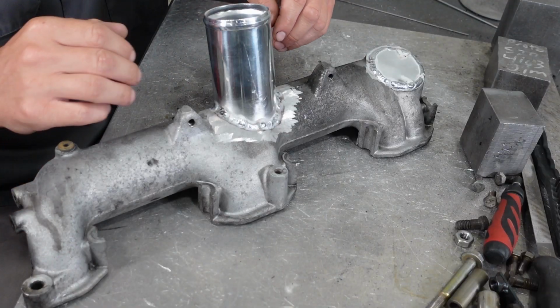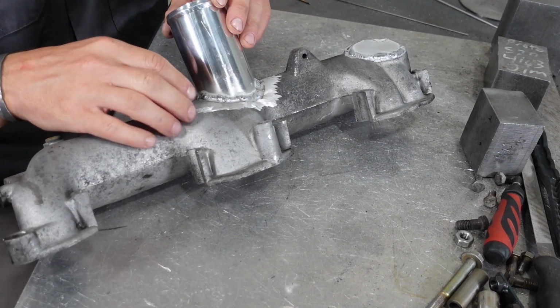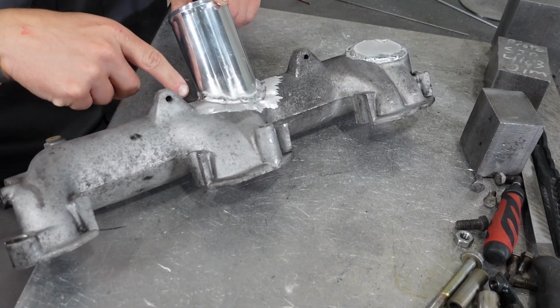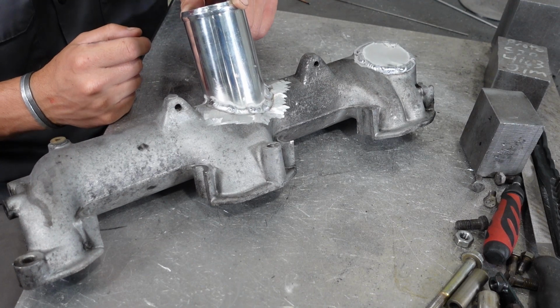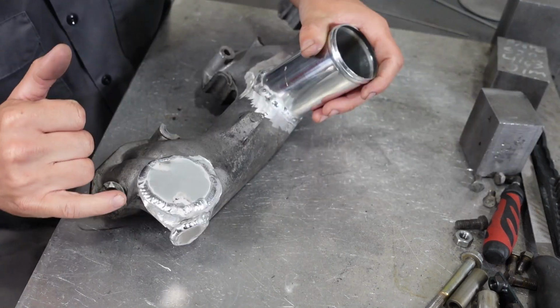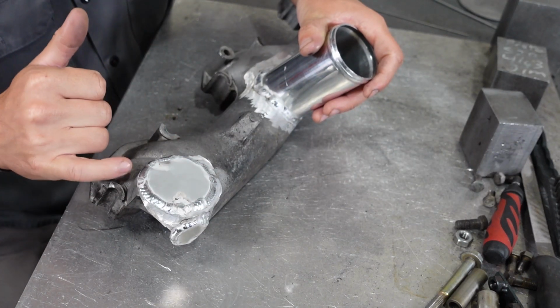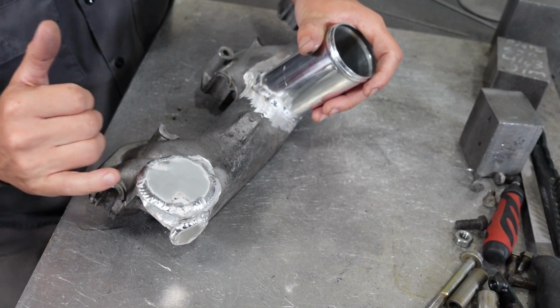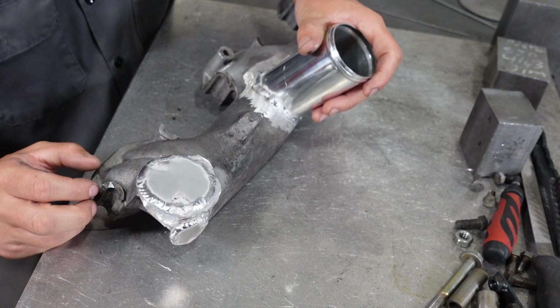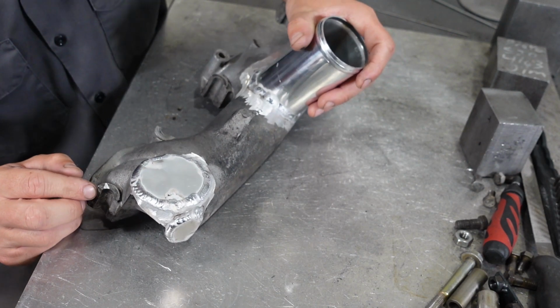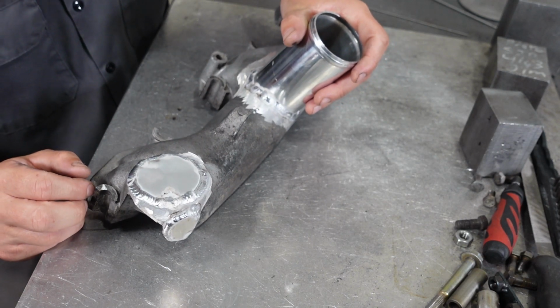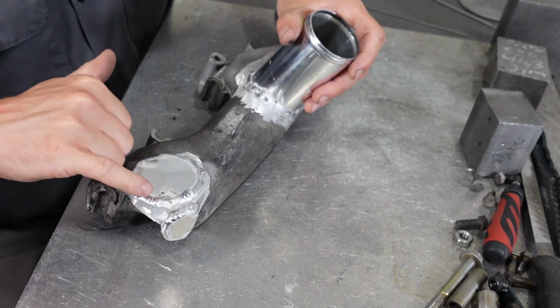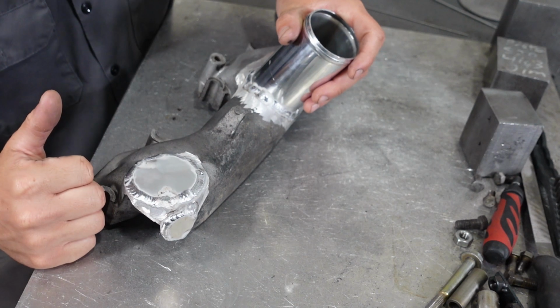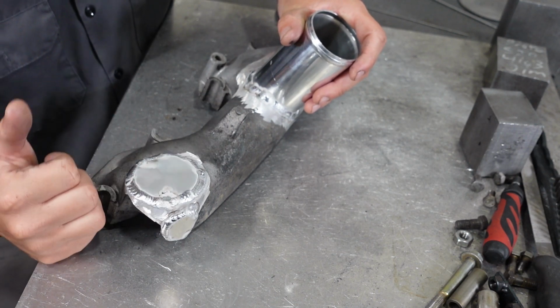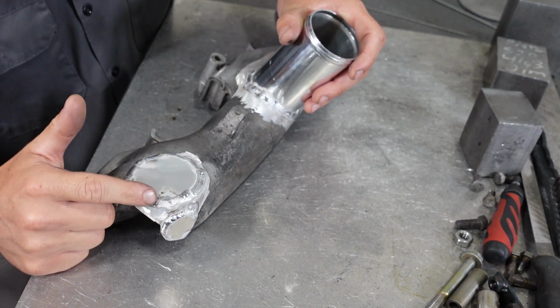All right, so here you can see we've finished welding. We've gotten this all the way around. I did it in multiple steps, let it cool down. Over here, same thing, multiple passes. And just as soon as you think you've cleaned enough material off so that you're not sucking in that dirty cast surface, well, think again. There was one spot on here. I pulled a little contamination in right here. It's actually from the inside.